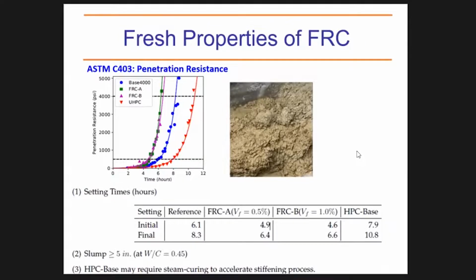But with the high performance concrete, the setting time is a little bit longer. But if you want to meet the time window for releasing the pre-stressing wires, we can just use steam curing. So this is all without the steam curing.